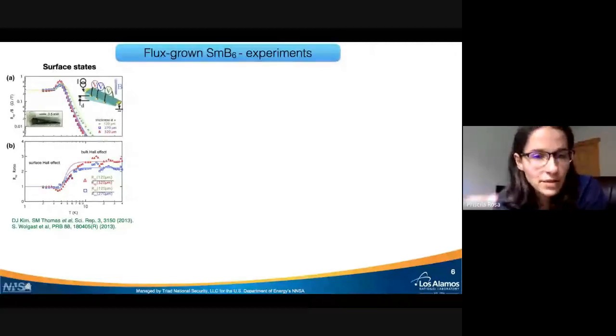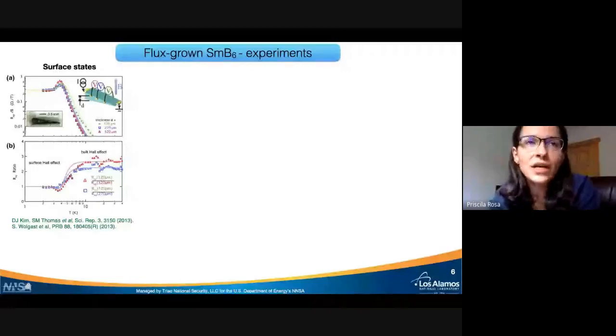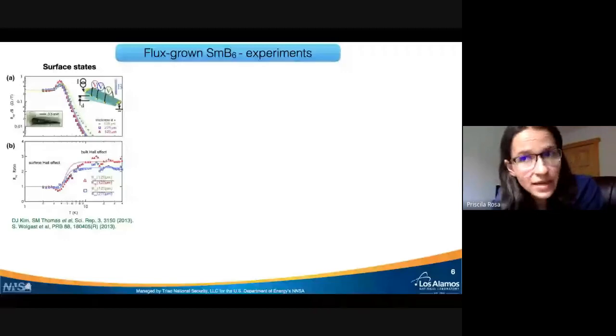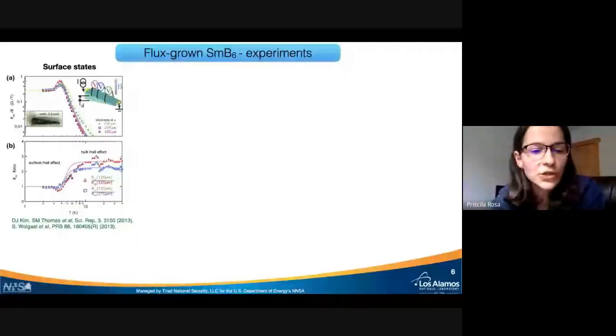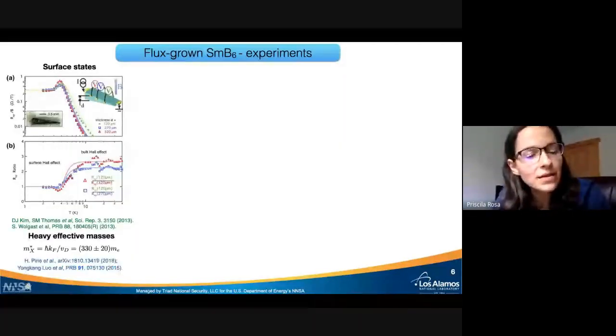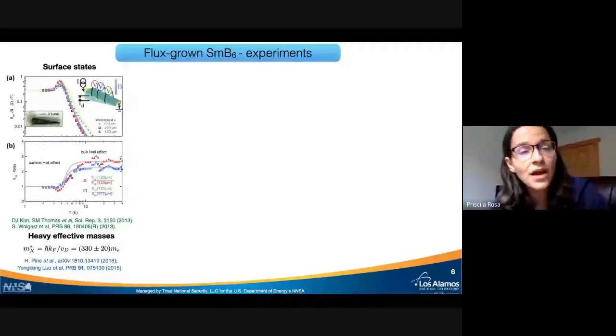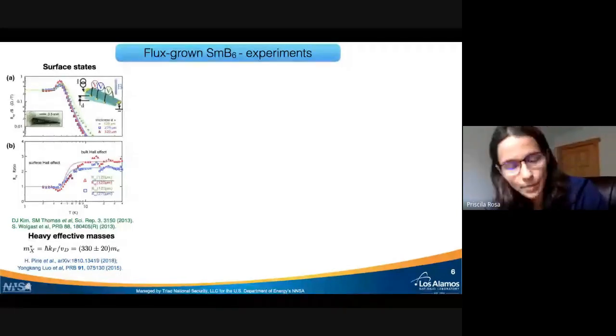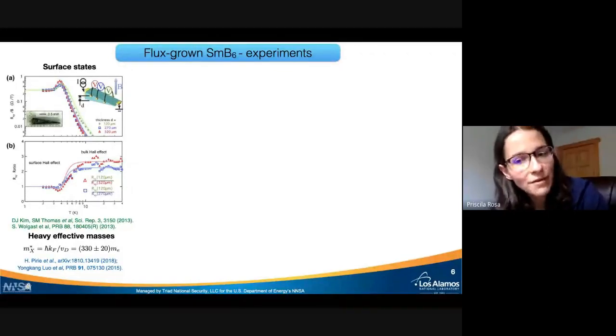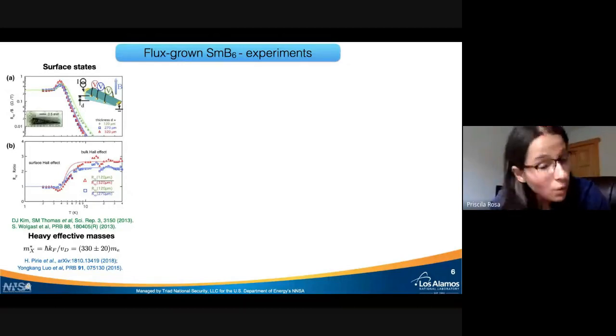The question that remained, for some time, was whether this is actually a topological surface state, because surface states exist without the need of topology, right? But one piece of information that is important that showed up more recently is that these surface states are actually heavy, which is something that you would expect if indeed it was coming from samarium, from F electrons. And I won't go into the details of these two papers, but